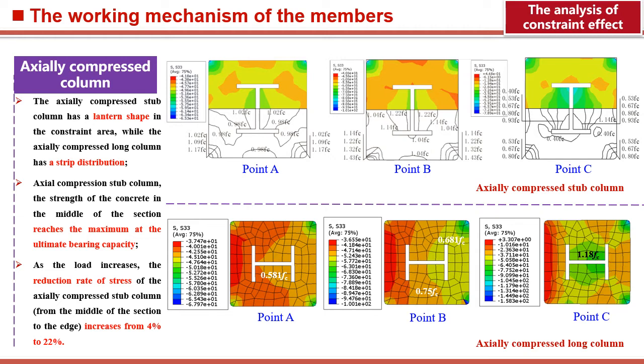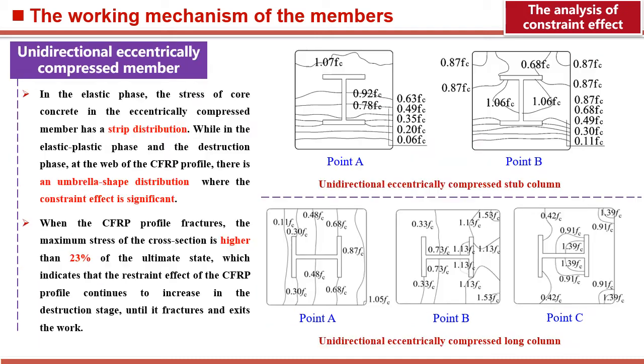In addition, the stress contour of the long column has a strip distribution, indicating that the restraint effect of the axially compressed long column is lower than that of the stub column. Moreover, the unidirectional eccentrically compressed member is analyzed. The stress contours in the tension zone are relatively evenly distributed in strips, while an umbrella-shaped distribution appears in the compression zone. In the confined area, the strength of the concrete has been significantly improved. As the stress increases, the scope of its distribution gradually increases.